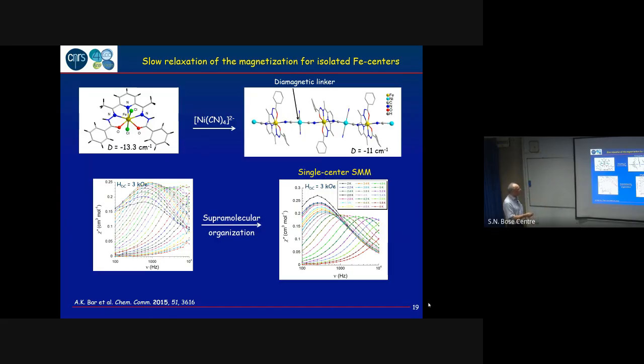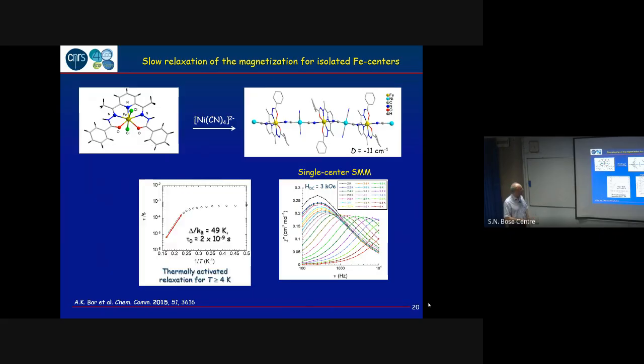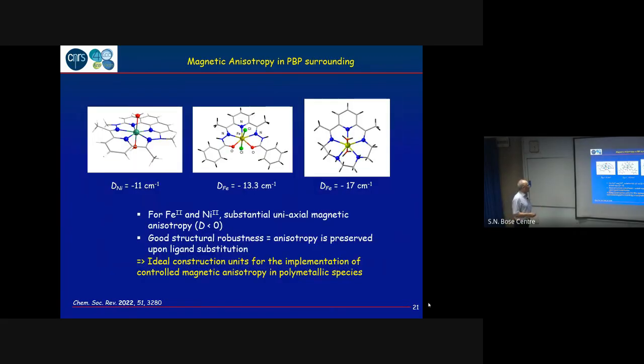This comes from the same molecule. It comes from this center. It's the same as here, but because there is no intermolecular interaction, now you have a clean behavior that is the one you expect, and that corresponds to what I have shown before. The numbers are there. So this is just to highlight that. And the second interesting point is that it shows that you can do chemistry without losing the intrinsic property of this complex because the geometry is there. Okay, so this is just to sum up what I was telling.